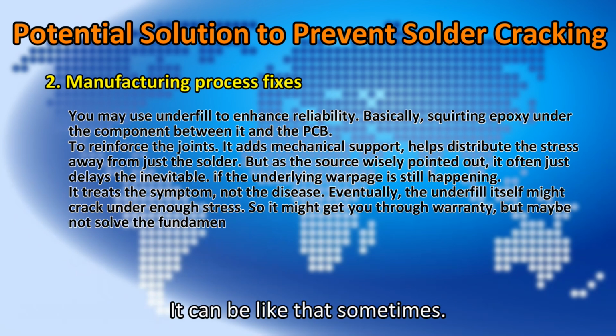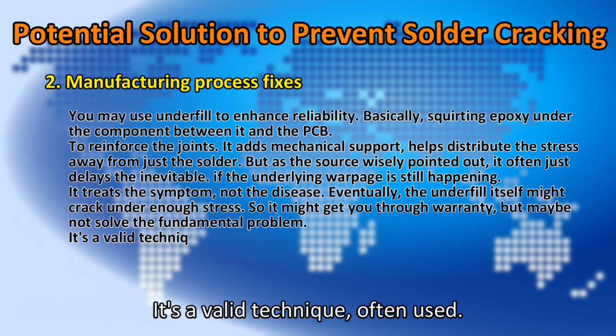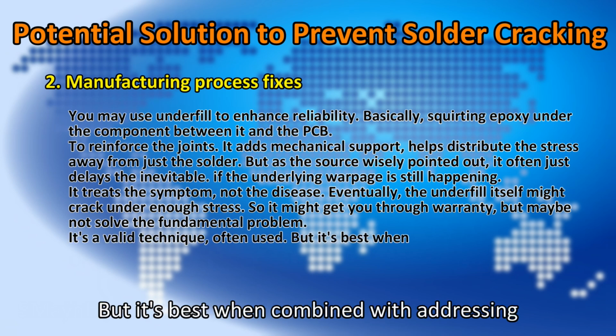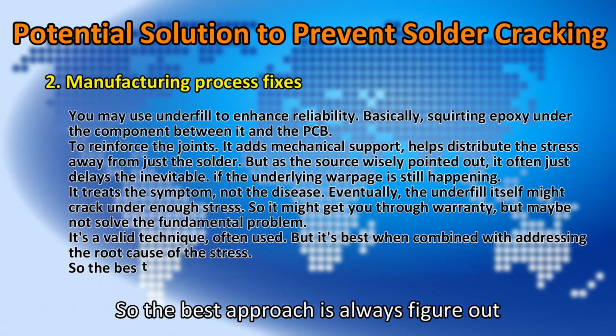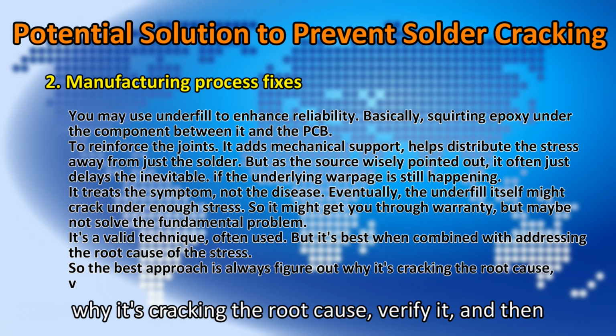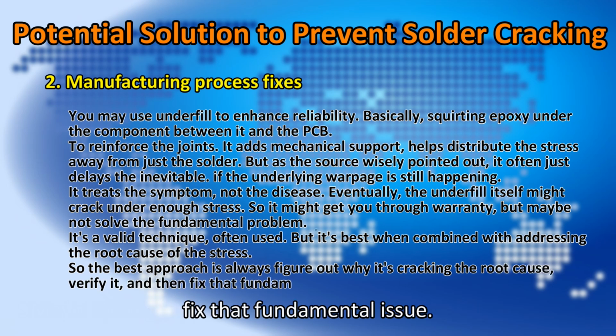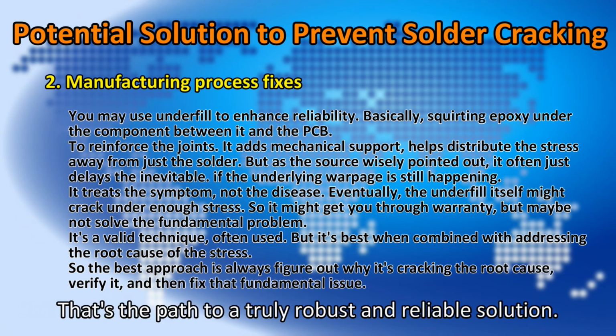It can be like that sometimes. It's a valid technique, often used, but it's best when combined with addressing the root cause of the stress. So the best approach is always figure out why it's cracking, the root cause, verify it, and then fix that fundamental issue. Absolutely. That's the path to a truly robust and reliable solution.